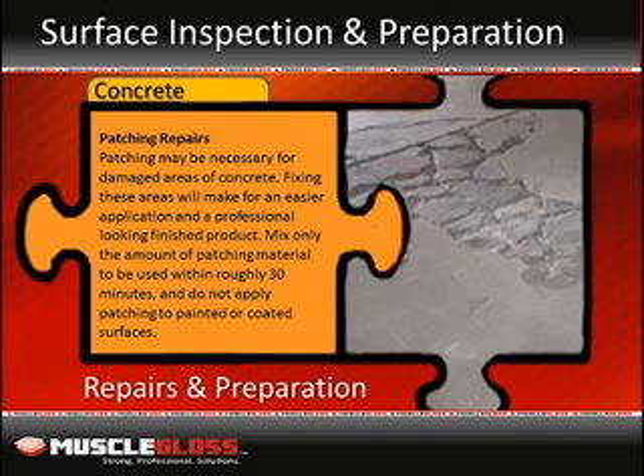Apply patching mix with a trowel using heavy pressure. Overfill joints slightly, then trowel smooth. For deep cracks, apply in quarter-inch layers. Allow to dry for 2 hours between layers. Clean tools immediately with water.